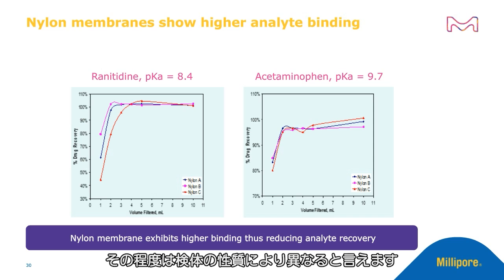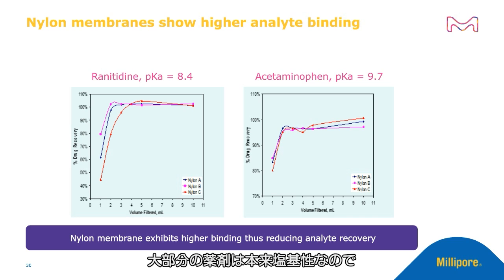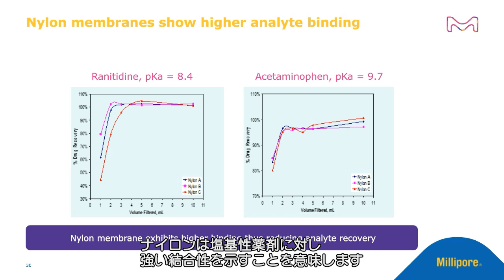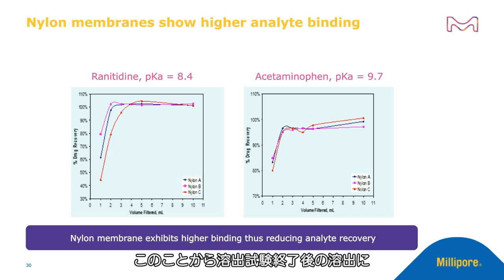Nylon membranes, due to their physico-chemical nature, show strong binding to different drug molecules, and this binding will vary depending on the nature of analyte. Since a large proportion of drugs are basic in nature, this means that nylon will show stronger binding to basic drugs. What it means for use in dissolution is that when we are trying to use nylon syringe filter for post-dissolution testing, it is advisable to discard larger volume of filtrate before the sample is collected for analysis, because it is easy to reduce the level of analyte binding once the filter is completely saturated.